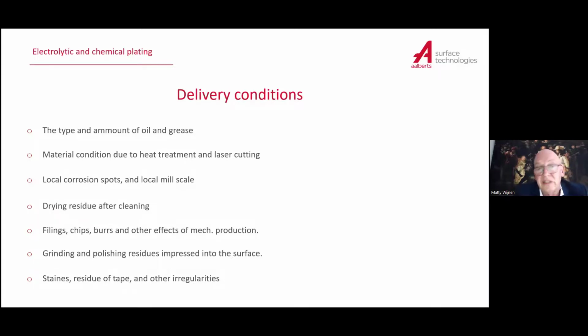Material conditions, laser cutting, as I told you, heat treatment. Beware if you use, for instance, nitriding of a material as one treatment and you want to plate it afterwards. Nitriding, iron nitride, is a ceramic and it's not platable. So you have to remove that. We have to aluminum blast it, so the complete nitriding layer is gone. So those are things which conflict.